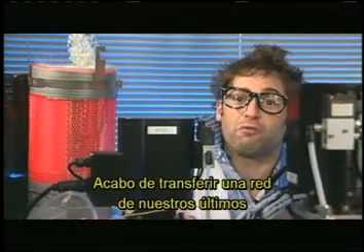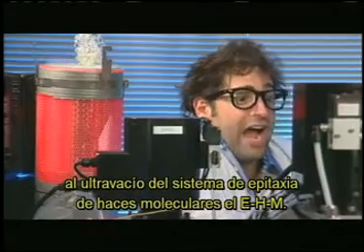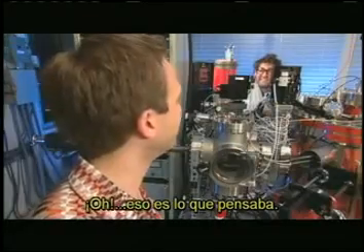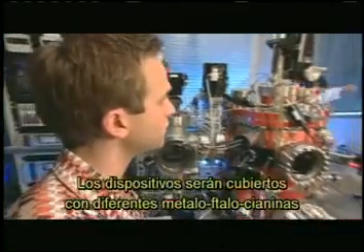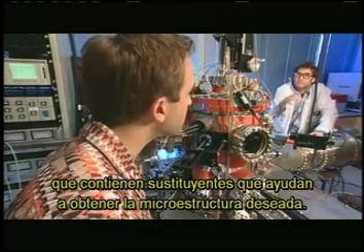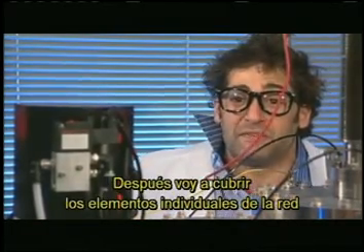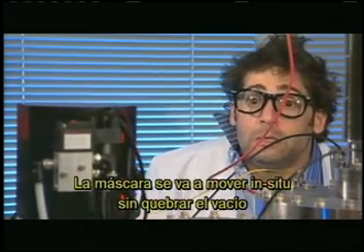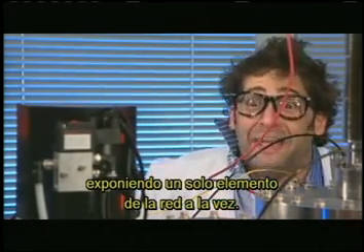I have just transferred an array of our latest nanostructured chemical field effect transistor devices from the load lock into the ultra-high vacuum section of the molecular beam epitaxy machine here, the MBE. Oh, that's what I thought. And then what are you going to do? The devices will be coated with a number of metallophthalocyanines that contain bulk substituent groups to help us achieve a desired microstructure. I'll be coating the individual elements of the array using a floating shadow mask positioned within 10 micrometers of the array. The mask will be moved in situ without breaking vacuum, exposing one array element at a time.